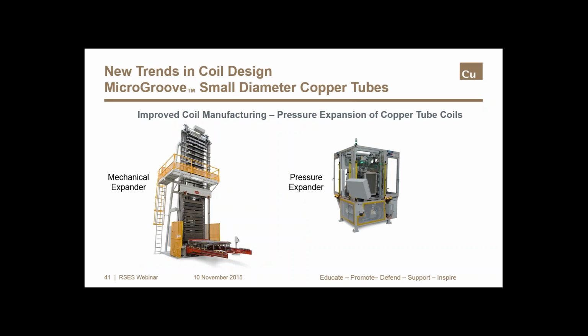You can see that the conventional mechanical expander requires significant vertical height as well as floor space. The new pressure expander has a smaller footprint and can produce coils much faster than the mechanical process. And because the pressure expansion of copper is extremely consistent and controllable, this process is especially well suited for copper tube coils.